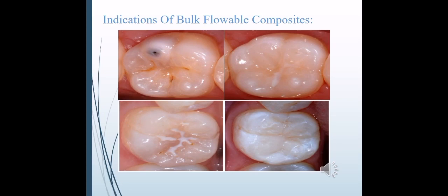As we can see in the first picture, we have a molar that has a lesion on its cusp. It was restored with SDR, and then a 2 mm capping layer of esthetic composite was placed above it. Below we can see a defective pit and fissure sealant that was removed and replaced with SDR, which looked more esthetic and more acceptable than the previous one. These materials could also be used for undercut blockout, repair of small defects in esthetic direct restorations, repair of small enamel defects, and repair of acrylic resin temporary materials.